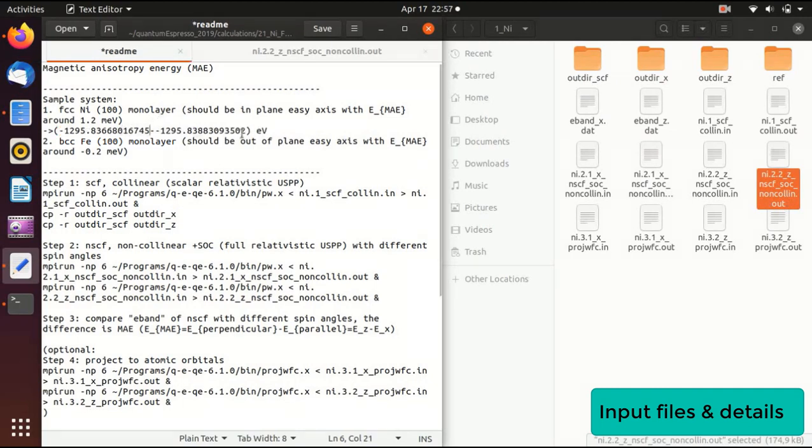And remember that in this case we have 2 atoms in a unit cell, so we have to divide it by 2, and then it is eV per atom, yeah. And then the result is actually 1.075 milli electron volt per atom, and this is actually consistent with the literature. But of course, if you really want to get a really nice estimation, you need to do a convergence test. And I suppose this 1.2 is also a rough idea. It is also not really converged.